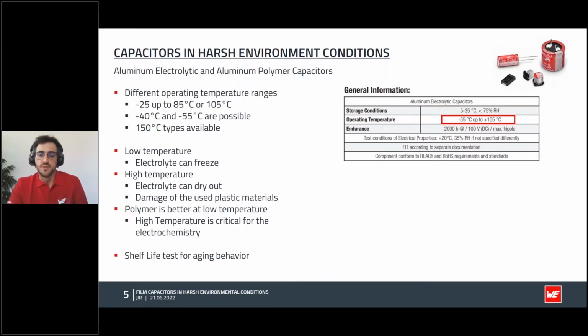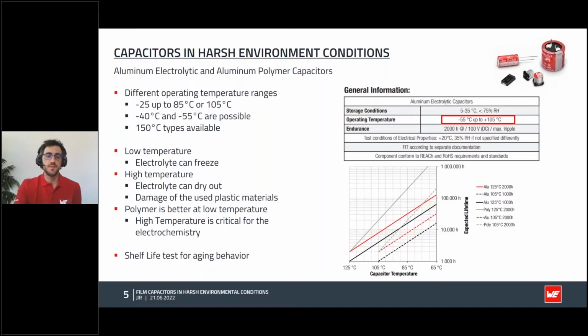In this diagram, you can see an estimation of the expected lifetime of different series rated for higher temperature. So operating lower and lower from the maximal temperature, the expected lifetime increases exponentially. Polymer parts are plotted in gray, and you can notice the exponential growth is even faster. So you can see the effect of the solid electrolyte on the expected lifetime.